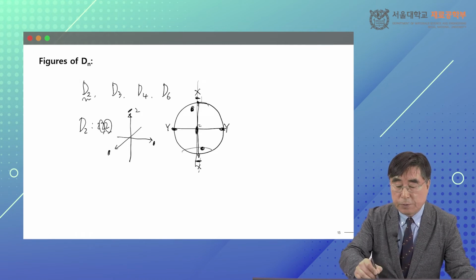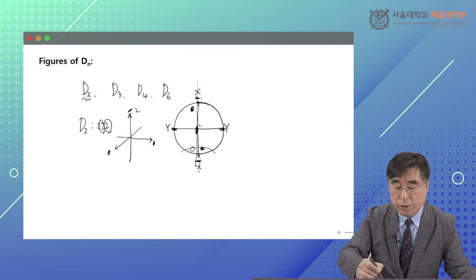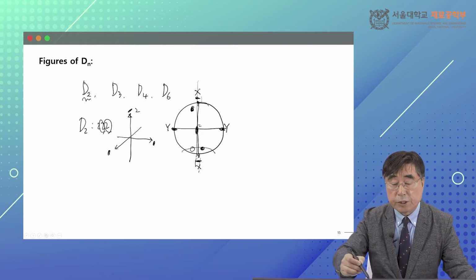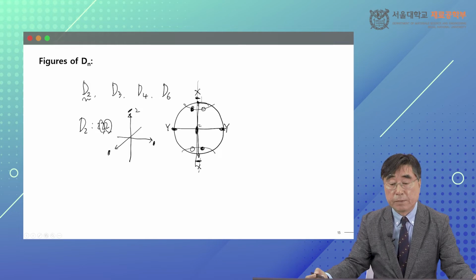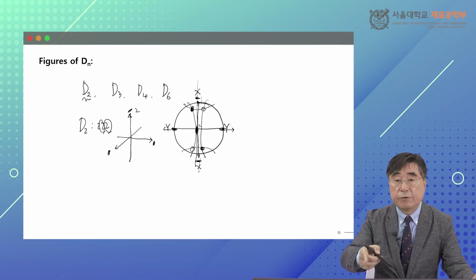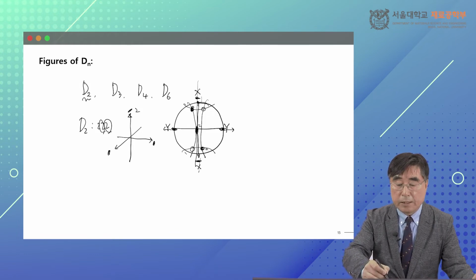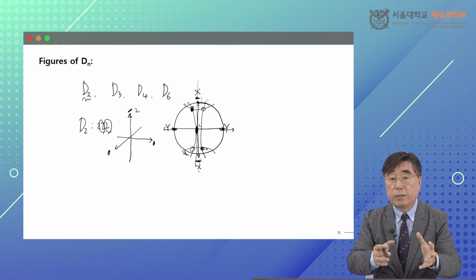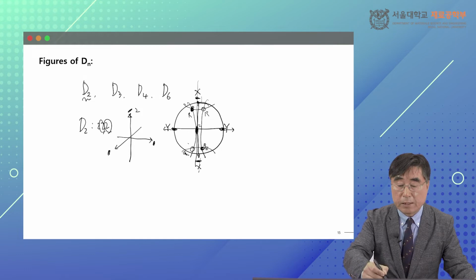Okay? So in this case, if I have a general pole here, twofold makes these symmetries. Now this x-axis operation is using the Wulff net, and you rotate 180 degrees along the rotation axis, which is in the plane. Then a pole is generated here, and this pole is generated here. So the multiplication factor is 4. Again, you don't have to do this y operation. You know immediately that there is twofold symmetry in that direction. So the multiplication factor is 4, and this is upper pole, and this is down pole, but this is all composed by the simple rotation. So all the right hand is maintained, and this one is right hand, this one is right hand, this one is right hand.